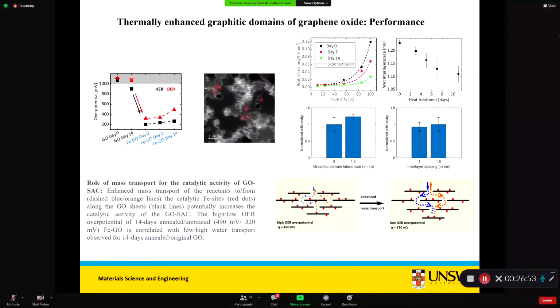We did this work, and when we did this work, this was very good work. And if you see in this TEM, we saw the single atom, the Fe. We intercalated Fe ions after that. In this one, what we see here is that we did the water flux experiment. We found that whatever we thought, that if we enlarge graphitic domains we'll have a higher water flux, it was not true in our case.